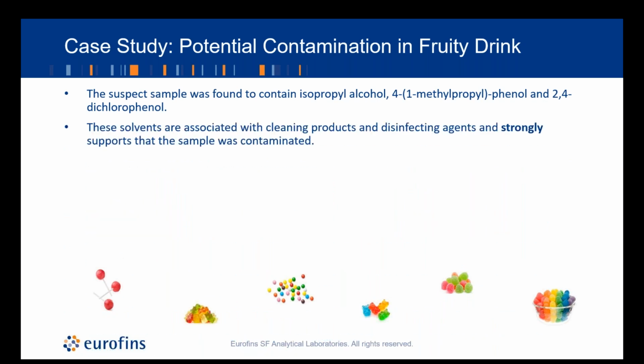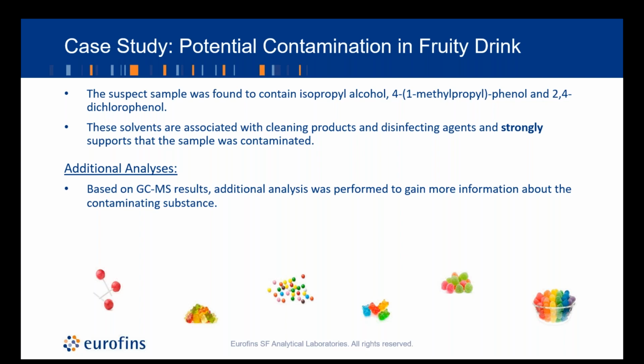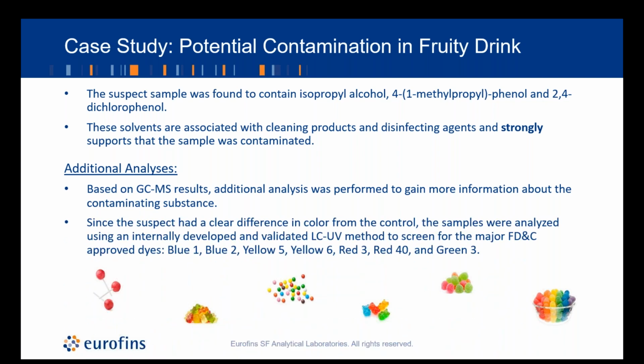These compounds are all solvents. They are associated with cleaning products and disinfecting agents, and this strongly supports that the sample was contaminated because these compounds are not something that you would find in a beverage product, and they're not potential degradants. They're not something you want in your product. So we have now established we do believe contamination has occurred, but we don't have any information from our GC data that would explain why we have a difference in coloration.